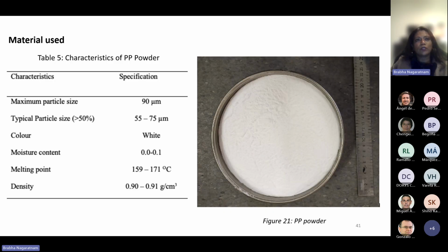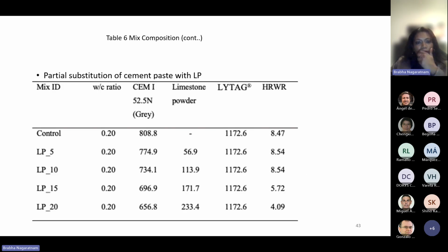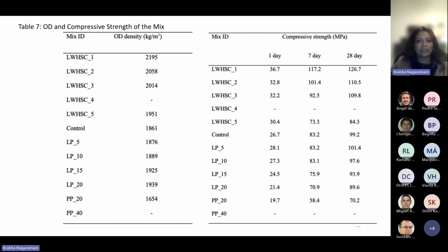In order to achieve a more sustainable mix, we are leading the work on polypropylene powder type of aggregate in lightweight high strength concrete. What we are doing currently in Northumbria is altering the properties of PP powder. As you know, polypropylene powders are hydrophobic in nature. They don't mix very well with water or in cement mix. So we are altering and modifying the properties to create a hydrophilic nature so that it will integrate better with the mixes. So these are some of the mix design and achieved 28-day strength.